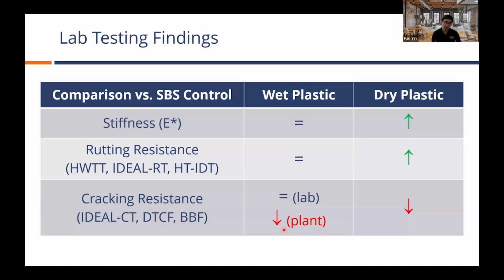If you look at the right side of the table, focus on the dry plastics. What we saw was a very significant stiffening impact from dropping in those plastic pellets. We saw higher stiffness, we saw better rutting resistance, but at the same time, on the cracking side, we saw a detrimental impact. So it's almost like with that stiffening impact, the material is more brittle and does not have good relaxation properties, and therefore it is going to sacrifice the cracking or the durability perspective of the mixture performance.